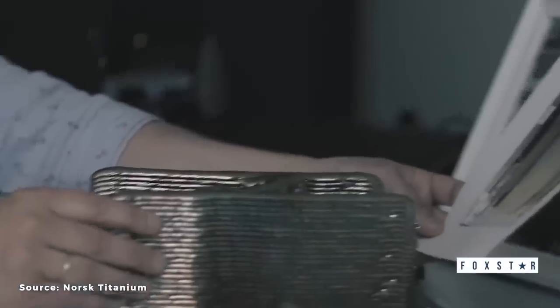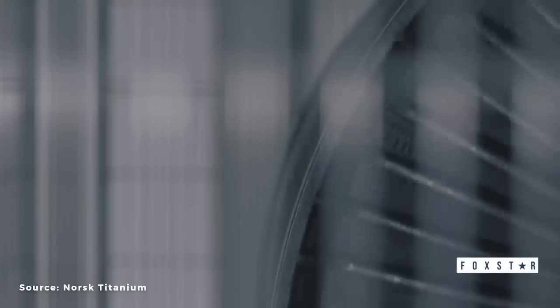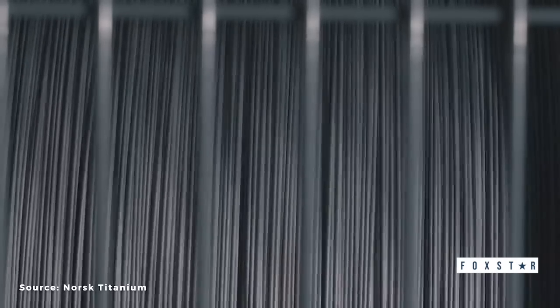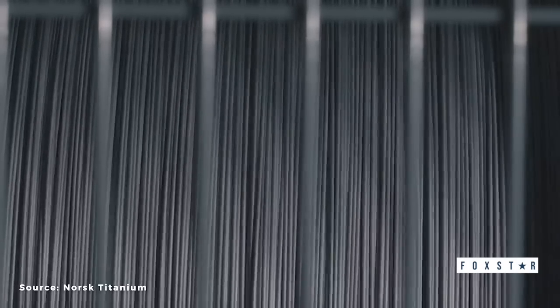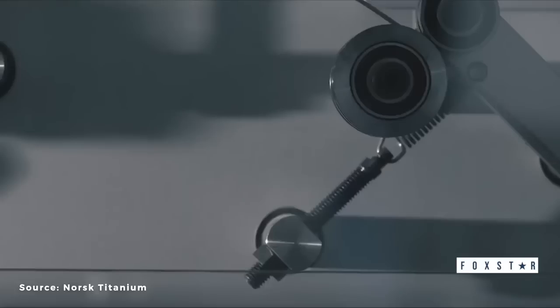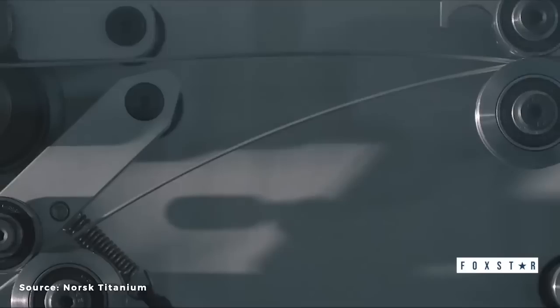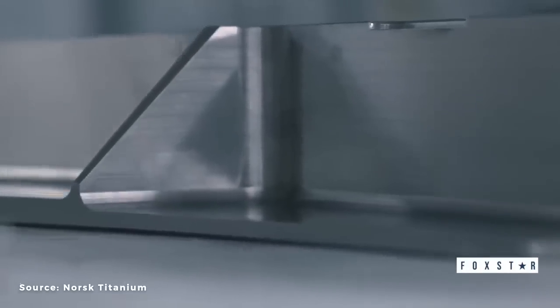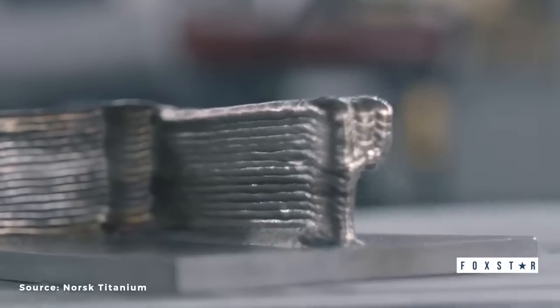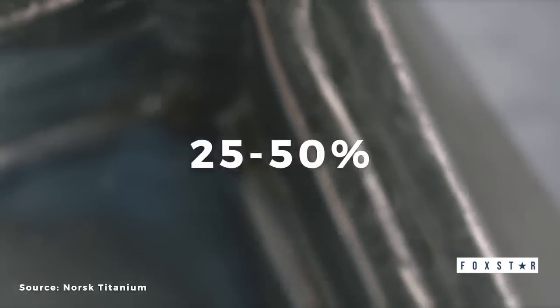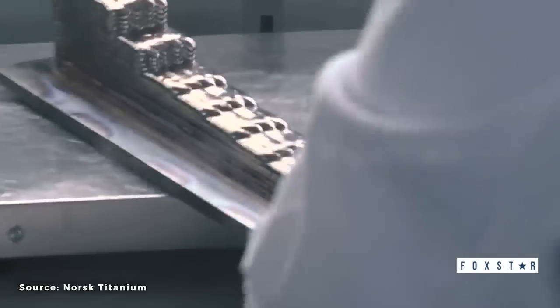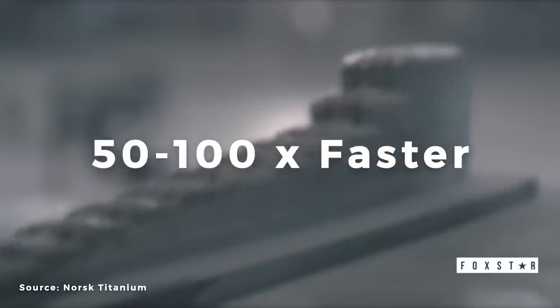Norsk has worked to improve this. Instead of using laser sintering with powder, Norsk have developed a revolutionizing, patented, wire-based metallic 3D printing system for titanium that they monitor with 600 frames per second cameras for quality control. These 3D printed parts are then machined down into their final shape, reducing the total titanium used by 25 to 50%, and their printing method is 50 to 100 times faster than the powder printing method. This process resulted in the first ever FAA certified.